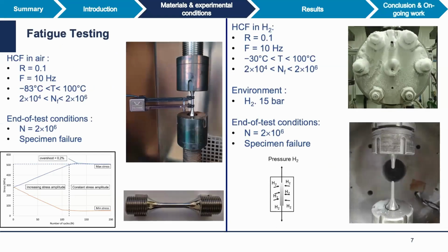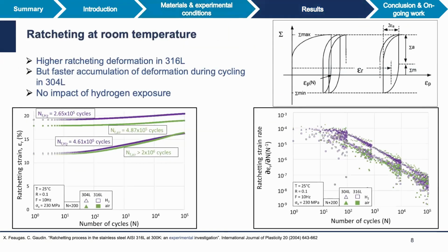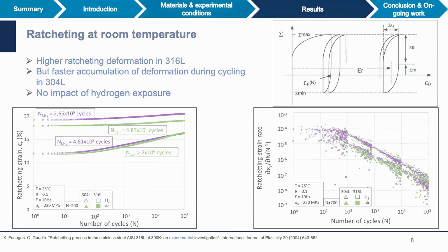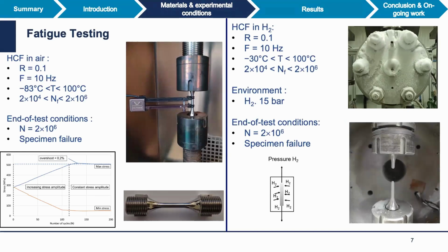As regards fatigue testing, we used the ECOMAT test rig available at PEPRIM and different test rigs which are under development in CETIM. So for high cycle fatigue testing in air, we use the following conditions: a load ratio of 0.1. That means that we have a positive mean stress, and this will be the cause of the ratcheting deformation. A frequency of 10 Hertz in order to reduce the test duration for this first screening. And for the results that I will present today, a temperature ranging between -83 degrees C and 100 degrees C.